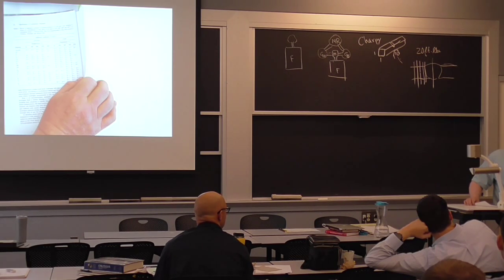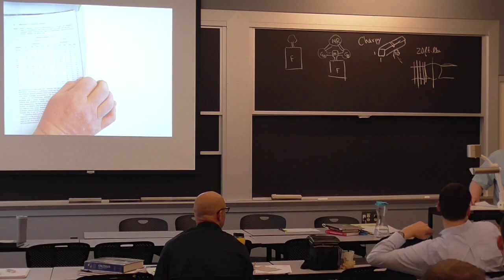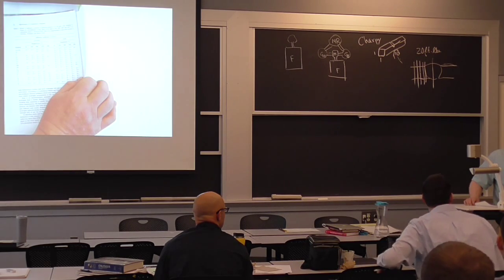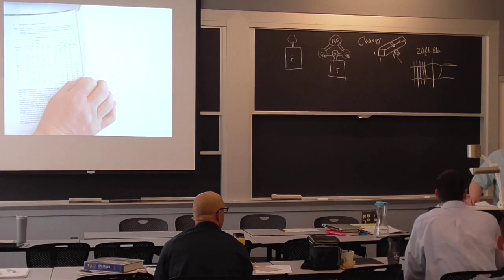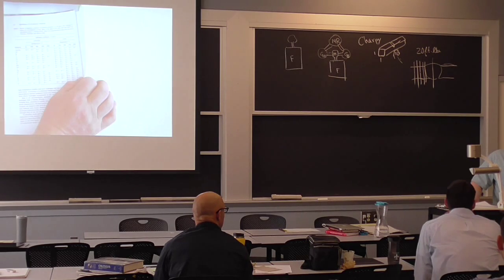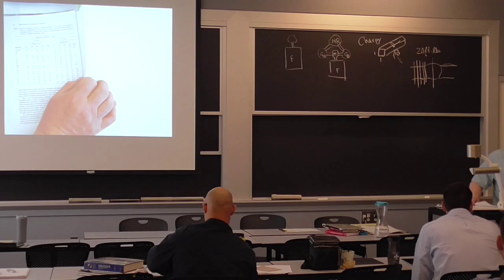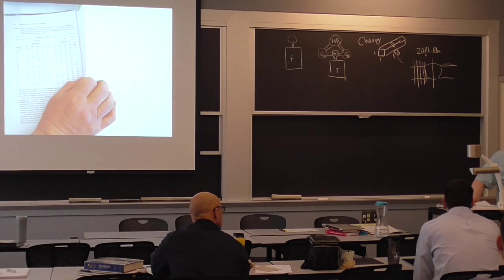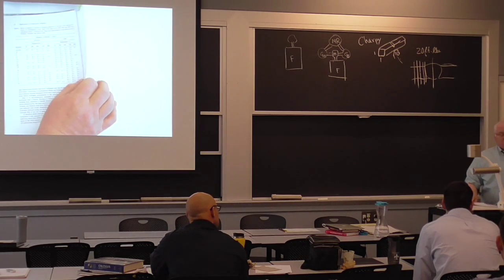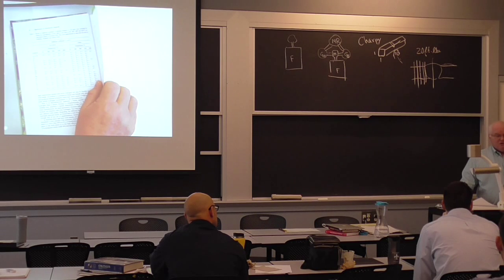And we'll see a little bit later that gas metal arc welding has even lower hydrogen, and that's one of the reasons to go to it. But at very high strength steels like aircraft landing gear or helicopter rotor mast, when you're at 250 KSI, you can tolerate less than 1 part per million, okay? And that can be from the steel making process.